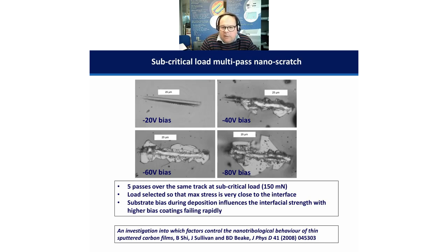But in reality, we as material scientists perhaps have a little more understanding of the fact that in the world of materials, we can't get something for nothing. And what this multiple pass wear test has actually revealed to us is that despite this being harder, this being softer, we have achieved that at the sacrifice of the interfacial bond strength between the coating and the substrate.